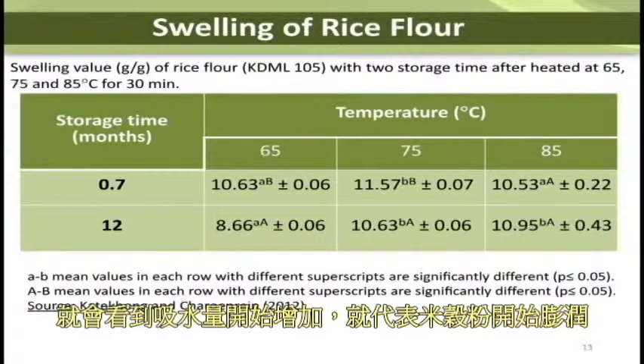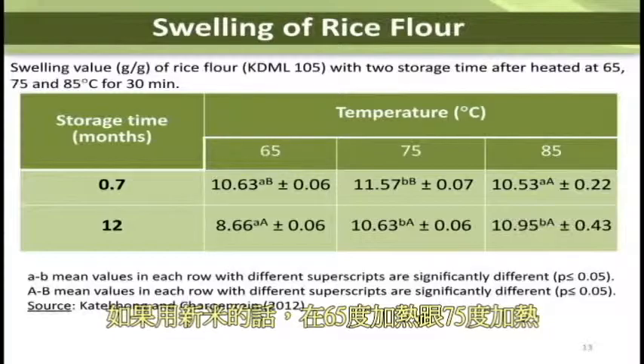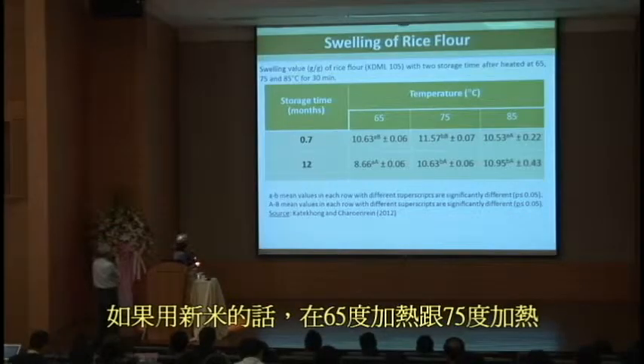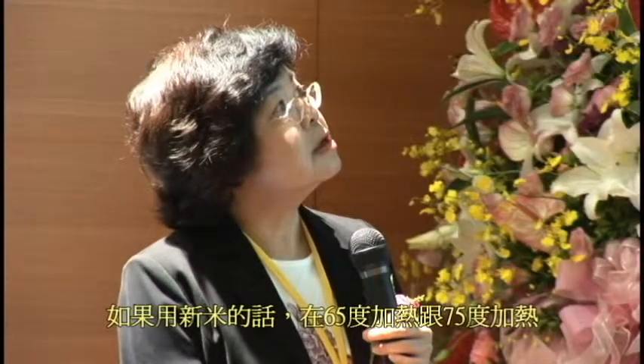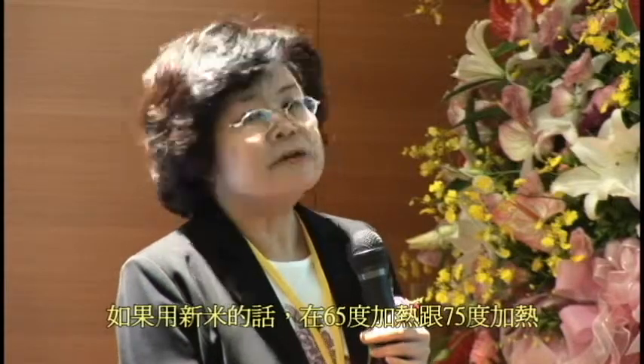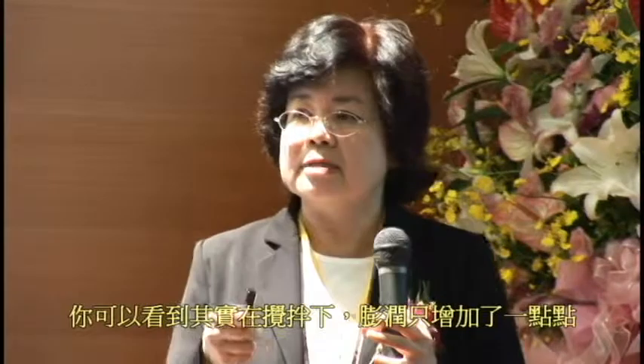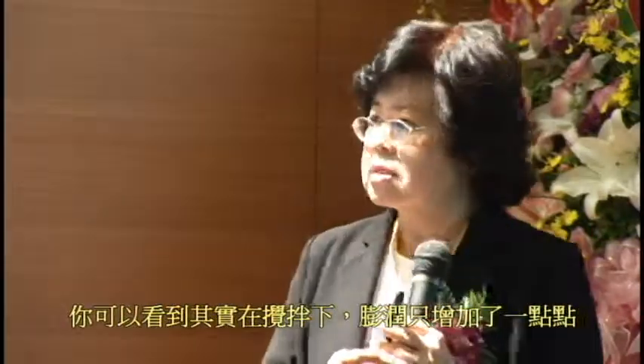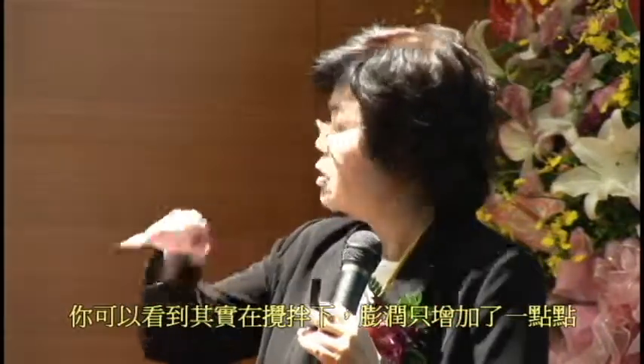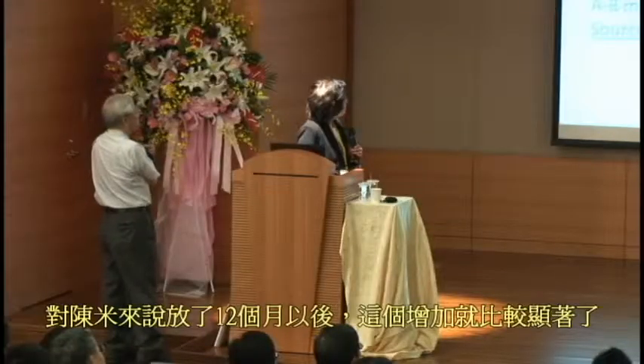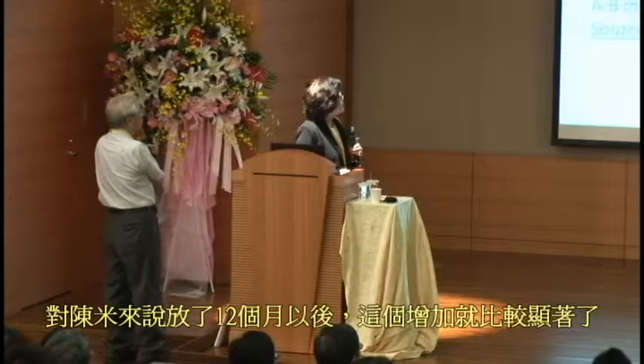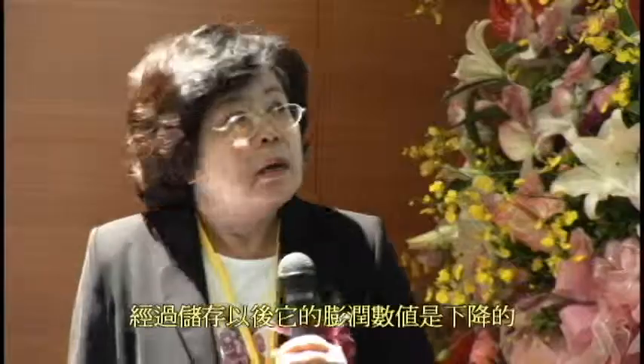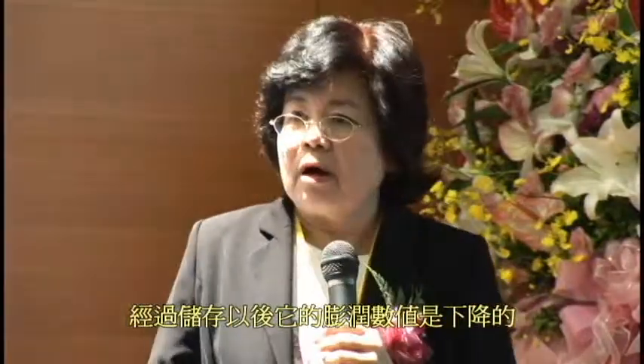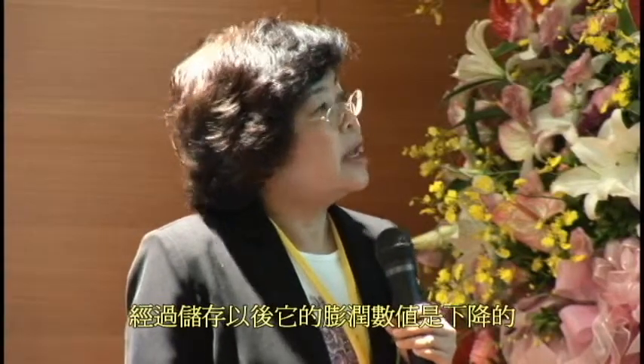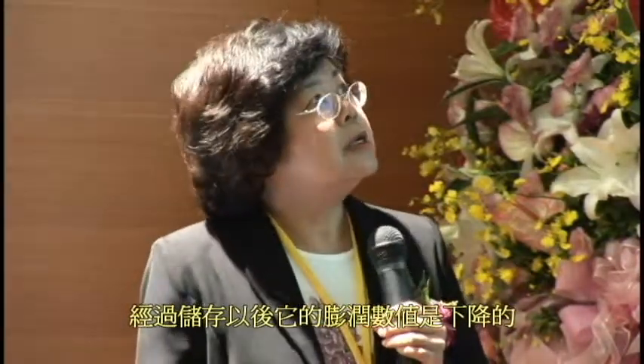In this table, the first thing we can see is what happens when we increase the temperature. Just look at the new rice flour. When we increase the temperature from 65 to 75, we can see that the swelling increases. This experiment was done with stirring for 30 minutes. The same as the aged rice flour, the swelling increased with temperature. But if we look at the effect of the storage, we found that when you age more, the swelling is less.